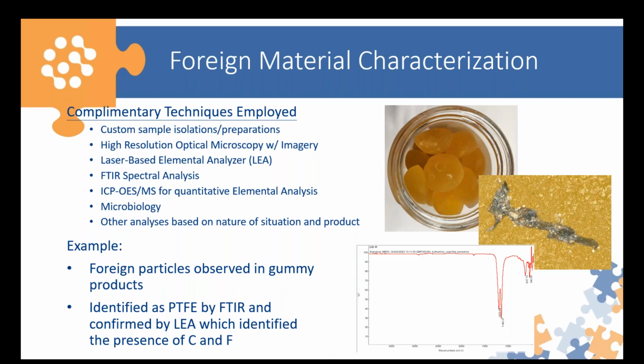So another example of this on the slide, I have some gummies. And these gummies were part of a pilot production. And what they found was they were seeing all these little specks throughout the gummies. And these were very small specks. They were very hard to see with the naked eye. So you can see the gummy in the middle here. If you squint, there's a little dark speck right on that gummy. And that was one of the bigger specks they were observing. But they really needed to know where these specks were coming from.